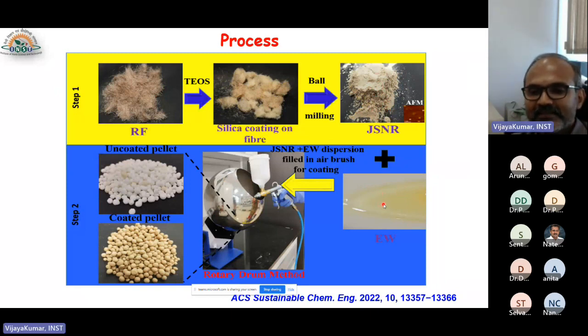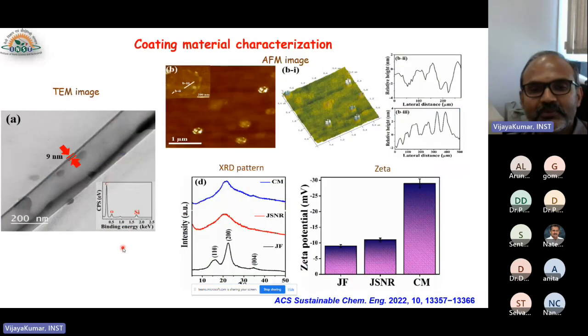Once it is mixed with the egg white and dispersed well, it is loaded into the air gun, and then this urea is taken into the rotary machine, and we optimize the temperature with the hair dryer, and then we optimize the spraying speed also, in such a way that you get a nice, stable coating on the urea. This milled material has been characterized with AFM, and it shows homogeneous spherical particles coated with silica and jute grafting.